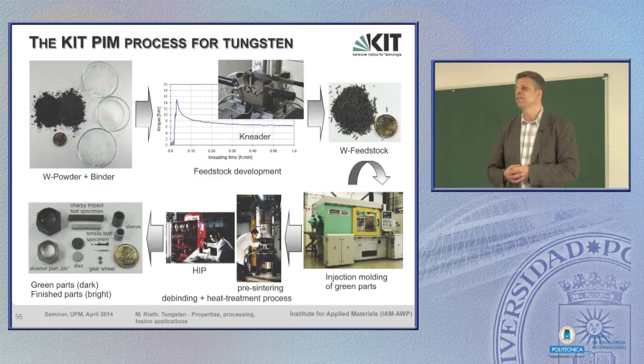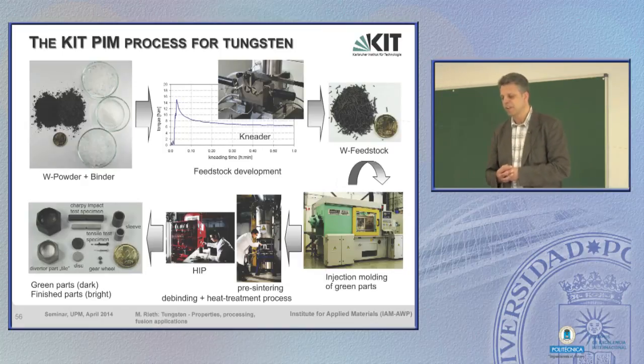Then, especially to produce armour parts of tungsten, we have developed a powder metallurgical process based on powder injection molding, which you might know. There is powder mixed with a binding phase, then this is kneaded to a mass. This mass, or this so-called feedstock, is then pressed into tools in a powder injection molding machine, and finally by sintering to remove the binder and HIP or further sintering, you can end up with very good finished parts.